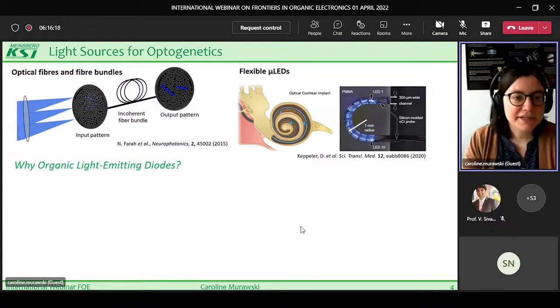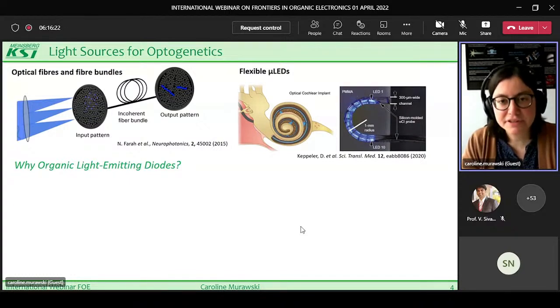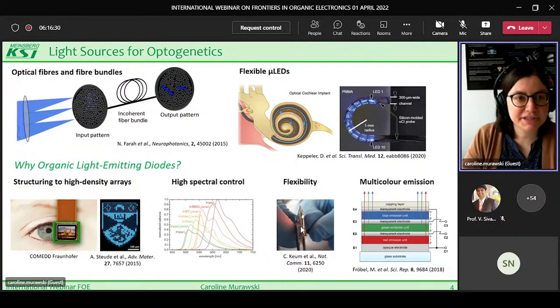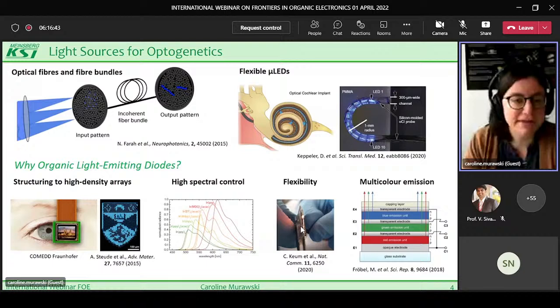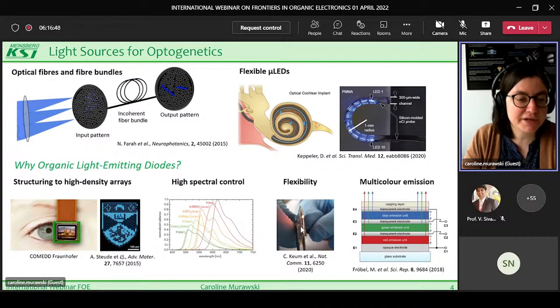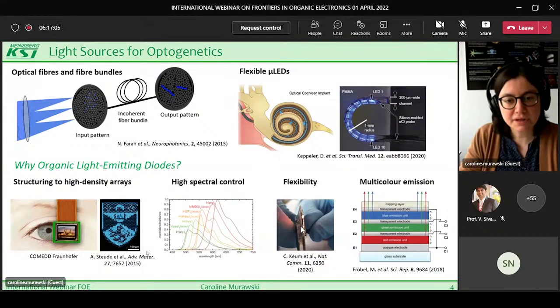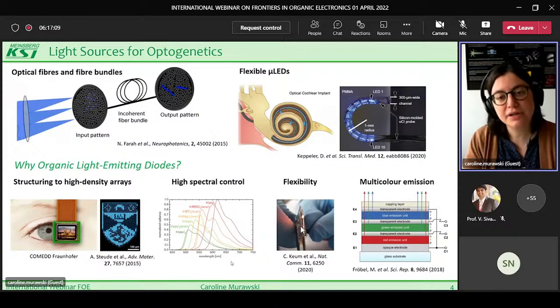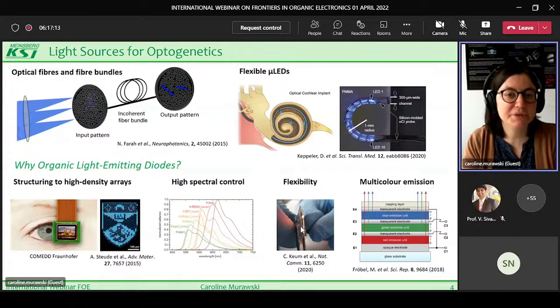And here our idea is to use instead OLEDs, and we've already heard this morning a number of advantages why OLEDs can be helpful, but I want to go specifically here into why OLEDs are useful for optogenetics. So first of all, as we already heard in Professor Adachi's talk this morning, OLEDs enable structuring to very high density arrays, also with losing less efficiency compared to inorganic LEDs if we scale them to small areas. You can see this nice example here of a microscopic OLED array where each pixel is 6 by 9 micrometers in size. This is smaller than the size of a neuron. Of course, OLEDs allow a very high spectral control, and this will be important in order to match the emission spectrum with the activation spectrum of the used light-sensitive proteins.